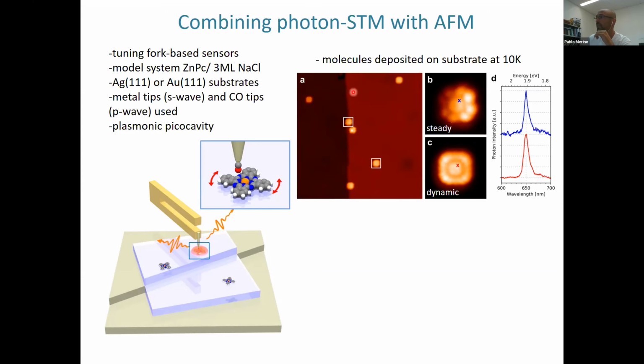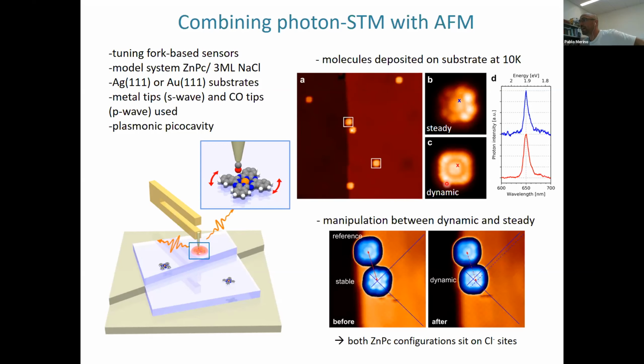And what we get for zinc phthalocyanine is that molecules can adsorb in 2 different configurations, which are steady and dynamic. The steady is fixed in an adsorption configuration, while the dynamic is rotating very fast between 2 chirally equivalent adsorption configurations. And for zinc phthalocyanine, the important part is that both molecules emit at the same energy. You see here that it is around 1.9, and for the steady and the dynamic we have exactly the same emission. We can do manipulations between the 2 adsorption configurations, and we also studied where they are sitting, and in this case, both configurations have the zinc metal atom on top of a chlorine site of the salt layer below.